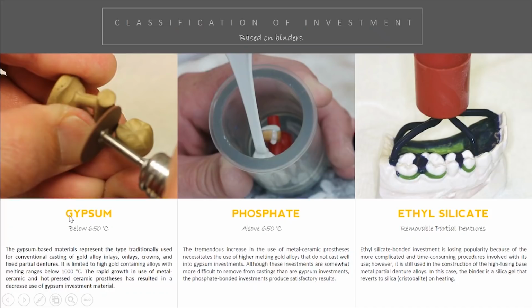Previously, gypsum bonded material was really popular because it tended to capture a lot of the good surface detail. While these dropped in popularity because of the fact that they couldn't be heated above this 650 degree threshold. The metals that were used in the past used to melt at a much lower temperature. So before the price of gold got very expensive, most of the dental materials, or the dental alloys or metals that were used in dentistry, were of a high gold composition. Since there's so much gold in it, it melts at a much lower temperature than some of the other metals that are being used today. So this allowed them to use this gypsum bonded material because it didn't need to withstand a high temperature, and also for the fact that it captured a little bit better surface detail.